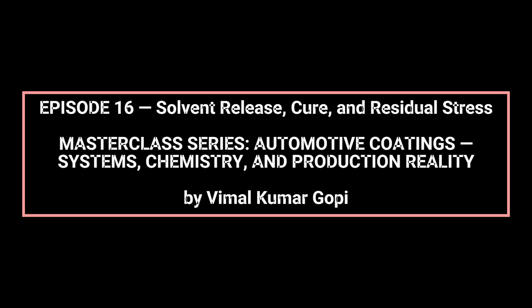Laboratory versus production behavior often diverges. Lab panels are thin, flat, and thermally uniform, allowing controlled evaporation and cure. Production car bodies introduce complex geometries, varying thermal mass, uneven airflow, and local environmental differences. These factors create spatial variations in solvent release and cure, leading to localized residual stresses that may cause orange peel, microcracking, or adhesion variation in production.